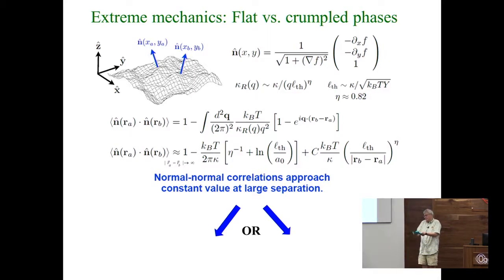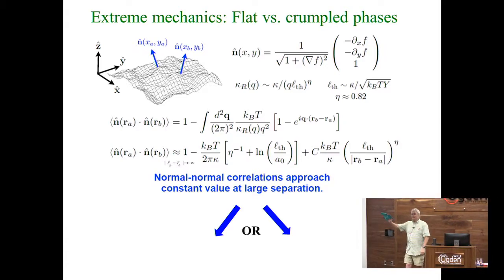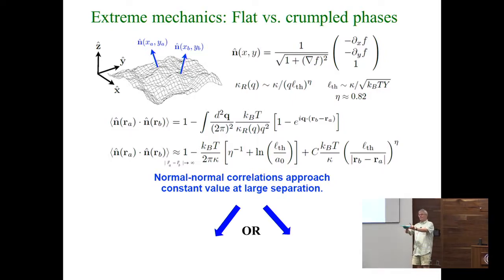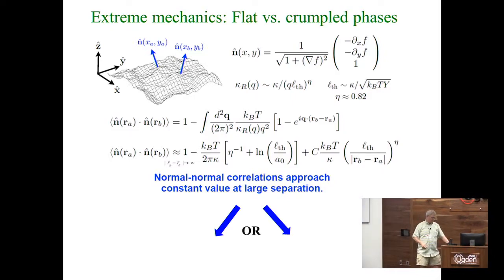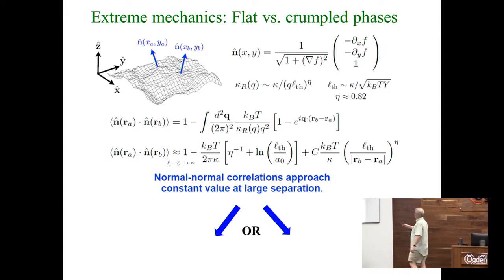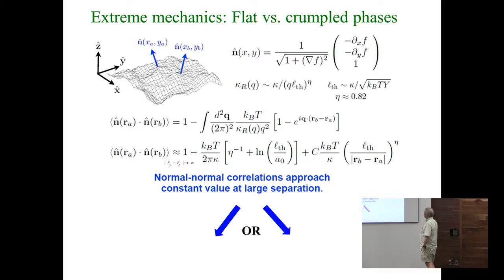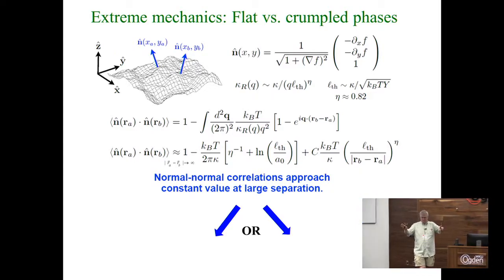if the paper is macroscopically flat in the thermodynamic limit of large paper size, the normal here should be correlated with the normal on the other corner. And as I pull the normals apart, I have long-range order, much like a spin system of Heisenberg classical unit vectors, a field of normals perpendicular to the surface. And you can work out the normal-normal correlation function. Here's the math that is just sketched for you here. Normally, if this bending rigidity, this elastic constant, were actually a constant and independent of wave vector, this would be logarithmically divergent. And there's a famous theorem that says in many two-dimensional systems that might have a broken symmetry, thermal fluctuations will overwhelm that broken symmetry.